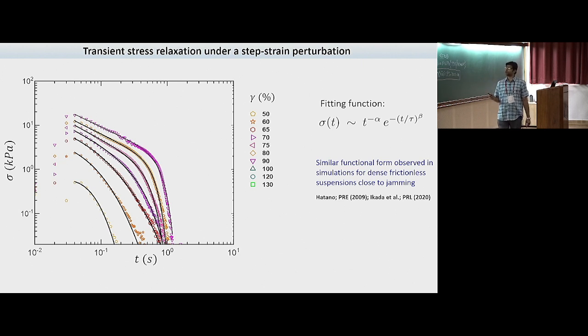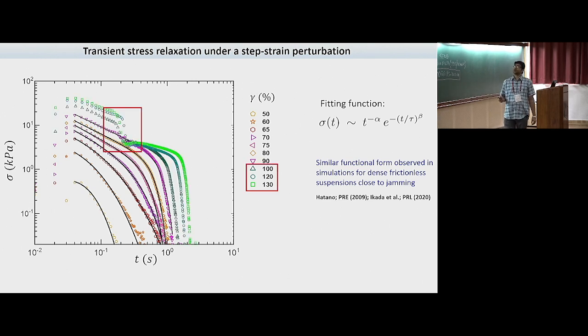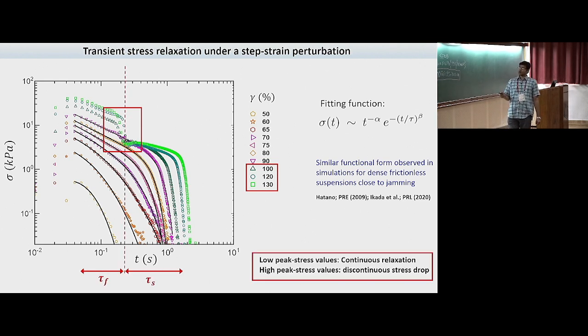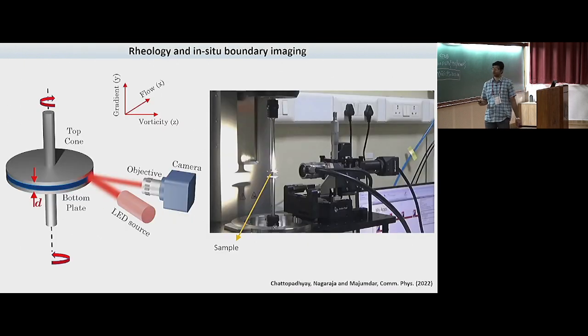Interestingly, if you focus on these large step strain magnitudes, we get a two-step relaxation. Your peak stress goes up, but there is a power law regime and then a sharp step, and then there is another part. This is a log-log scale, so this step can be very significant; in some cases it can be more than one order of magnitude. From this we define two time scales: up to this step, tau f, the fast relaxation time, and the remaining slower part, tau s, the slower relaxation time.